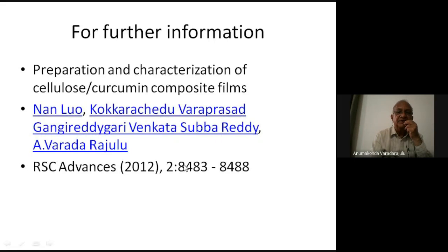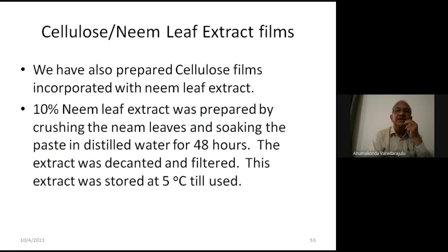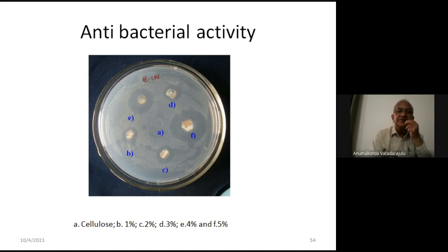in RSC Advances. Then we used neem leaf extract as the second component in cellulose. We took 10% leaf extract, dipped it and then dried, and it also showed very good antibacterial activity against different concentrations of this leaf extract, and a very clear zone is formed. So this can be used as antibacterial packaging films, both turmeric and neem extract films. And another advantage is they're biodegradable. They're antibacterial as well as biodegradable and so on.